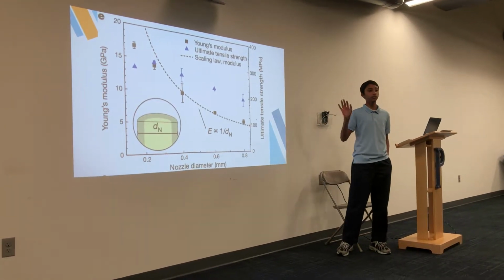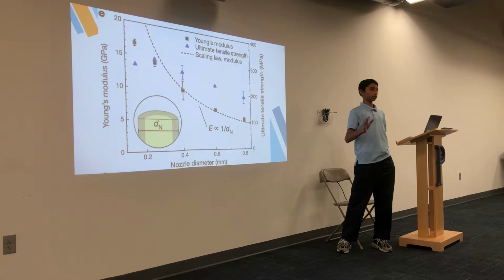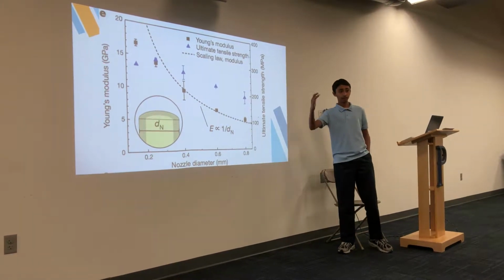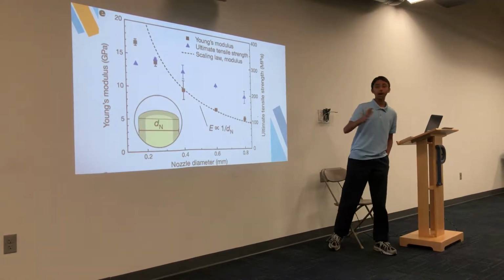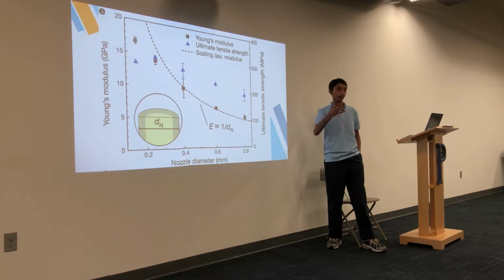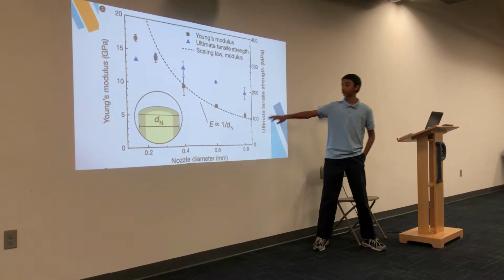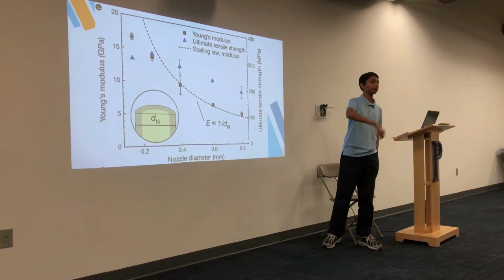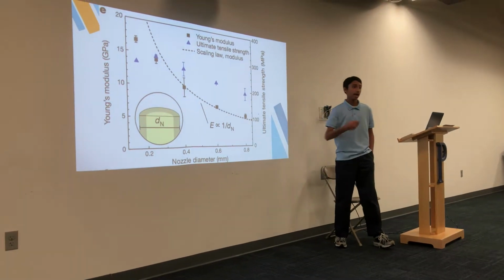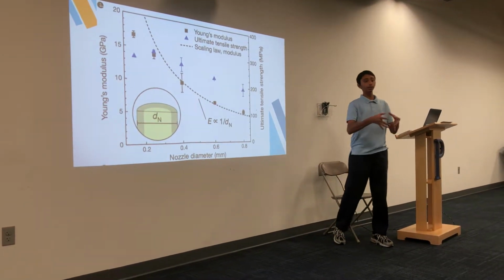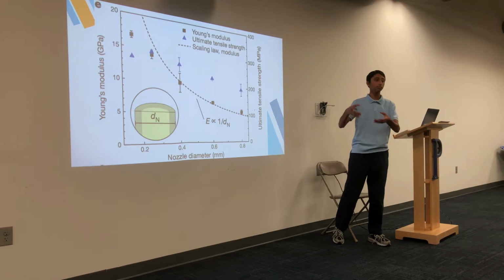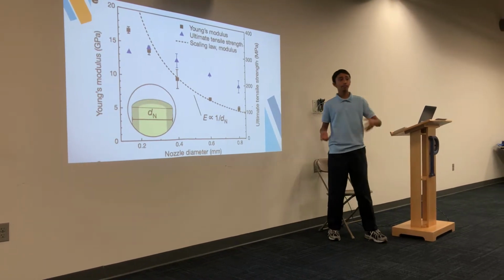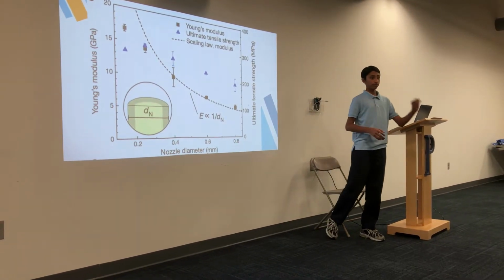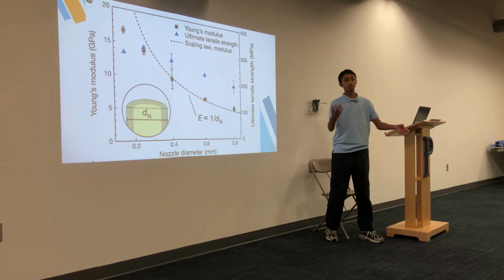The test here is to measure, in a layer of a certain height and of a certain dimension, how the nozzle diameter affects that strength. So the thinner nozzle diameter means that effectively there are more lines of filament. And if you think about it, a bundle of twigs is going to be stronger than one big thick twig, because you're able to share the weight evenly among the smaller twigs than you are in the bigger twig.